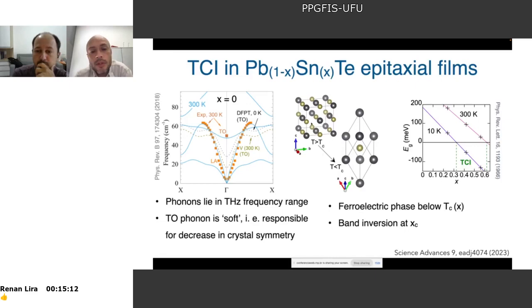Also, this system suffers a structural transition with temperature. So the frequency of this phonon becomes lower with decreasing temperature. And this is because the crystalline structure changes from cubic to rhomboedral, like this one, at a given temperature that we will call Tc. So there is a critical temperature where the crystal transforms like this, and then it enters a ferroelectric phase. So this material is ferroelectric below Tc.